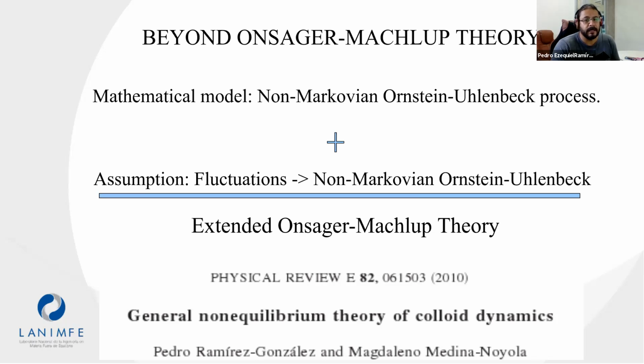Well, the standard approaches of statistical thermodynamics are not able to capture any of the features described previously. Necessarily, we need to develop extensions of statistical mechanics where fluctuations are included in the description of the system. One of the most important attempts at developing a fluctuation theory is the Onsager-Machlup theory of thermal fluctuations. However, such a theory is only useful for relaxation processes which are very close to equilibrium. So in order to have a good picture of the strong deviation from equilibrium observed near the glass transition, we need to go beyond Onsager-Machlup theory. Now, let me tell you how to make such an extension.